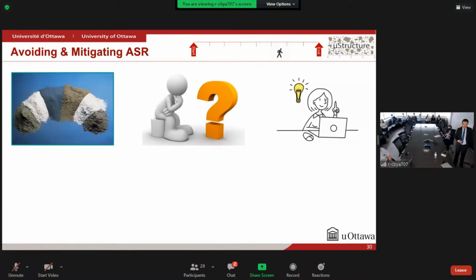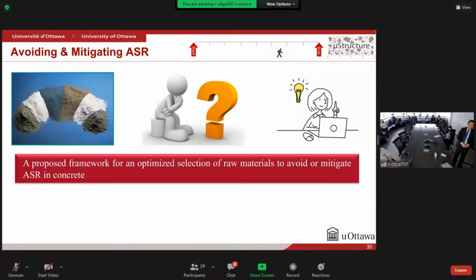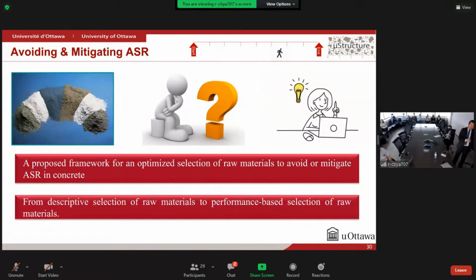So we saw that we can change ASR development once we treat the surface of the concrete. However, with the results here and also with the data from the literature, it's evident that prevention is the best solution. So at the end of this research, we would like to propose something to enhance the prevention against ASR. And for that, we propose a framework for an optimized selection of raw materials to avoid or mitigate ASR in concrete. In other words, we would like to go from a descriptive selection of the raw materials as in the CSA table to a performance-based selection of the raw materials.